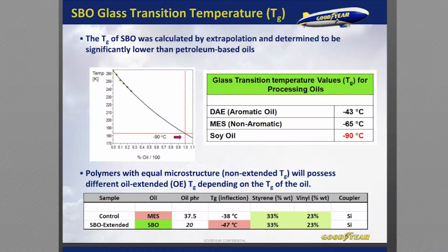What else is unique about soybean oil? Well, since it's a vegetable oil, it's a triglyceride. The glass transition temperature is far lower than the traditional petroleum-based oils. The glass transition temperature is the temperature at which a material goes from rubbery to glassy. So obviously, the lower the glass transition temperature, the softer the rubber will stay at these very low temperatures.